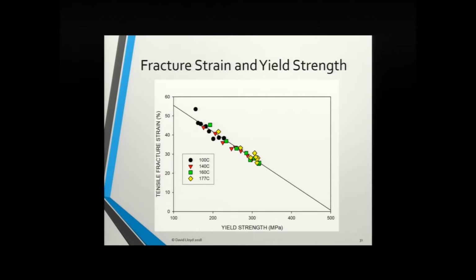That data point there, it's not an outlier, it's for very short aging times at 100 degrees C. And it's in a transition point between artificially aged, and this is very likely artificially aged, and naturally aged material. And the scaling line for naturally aged material is different to that for artificially aged material. I'm not going to go into this, but that's the way it is. So that data point is actually correct, but there'd be another line coming down here for natural aging. If we had natural aging data, it would track on a different scaling line.